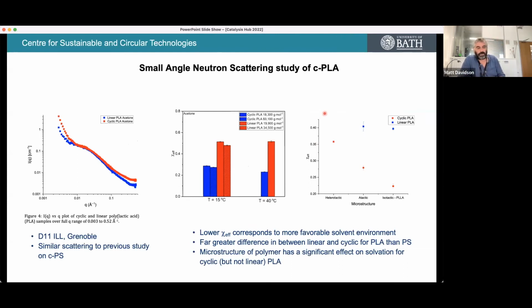Philip, in collaboration with his co-supervisor, in fact, Karen Edler, has done some small angle neutron scattering, some SANS, on these samples. Because we have access to some very well controlled cyclic PLA samples, which have never been looked at in this context before, it's quite interesting to look at them. So he recently did some experiments on D11 at ILL in Grenoble, and here's some data from those experiments.